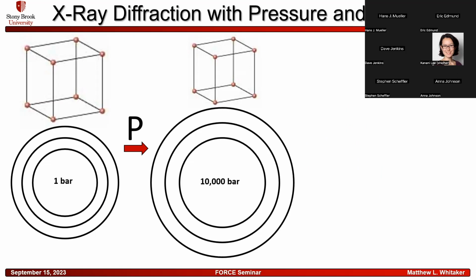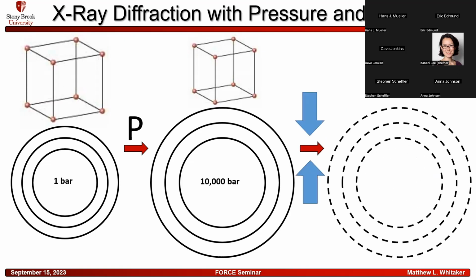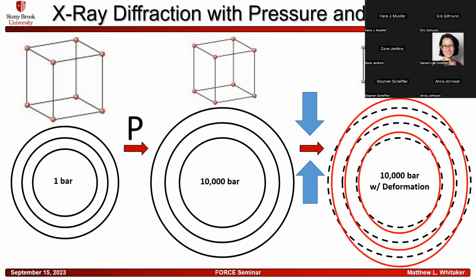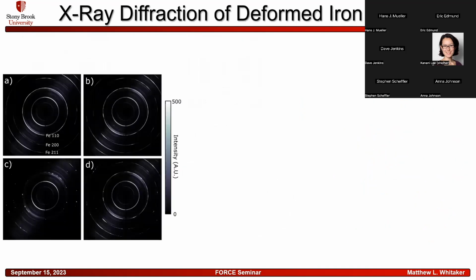So now, once we're at high pressure, we're going to add that deformation field. And those perfect circular rings then begin to deform into ellipses, where the d-spacings between the atoms, the atomic planes, are smaller in one direction versus another. And this is what we're looking for in these experiments. So it's a little bit difficult to see with the naked eye because it's relatively low pressure and the deviations are relatively small. But that is exactly what we see in the data that we collect from this experiment.